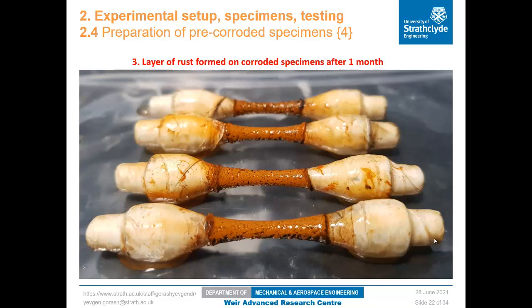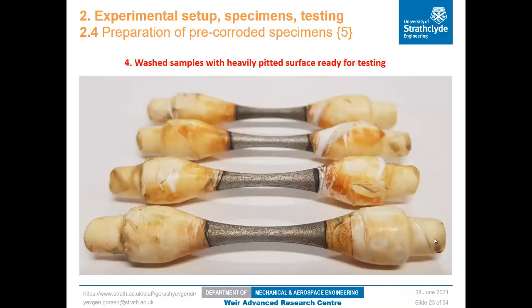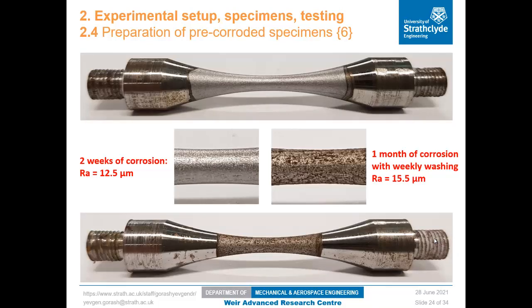And this photo shows that the layer of rust is much thicker than in the previous batch. There was much more rust in the seawater solution as well. Then after the samples were taken from the water, they were washed and cleaned, but still some rust remained on the samples, as seen here. When comparing the second batch of the samples with the first batch, the 1 month of corrosion with weekly washing has resulted in deeper pits that can be seen in this photo, and the roughness was 15.5 micrometers against 12.5 for 2 weeks of corrosion. So these two batches of samples also produced different fatigue testing results. The next section tells about the obtained fatigue results.